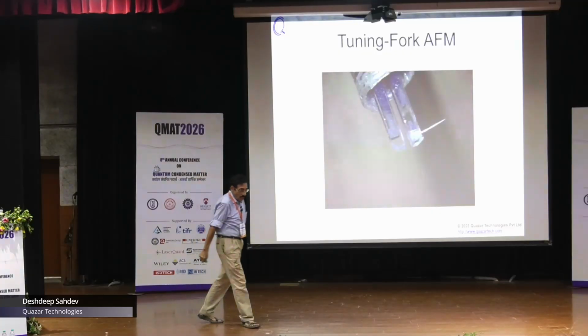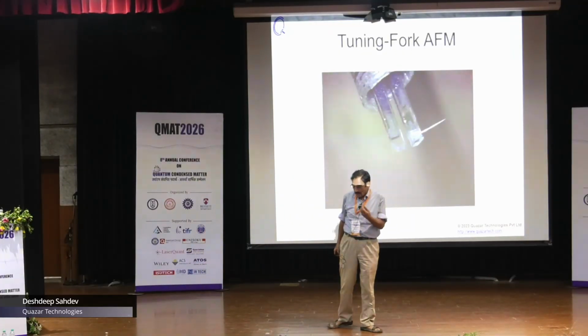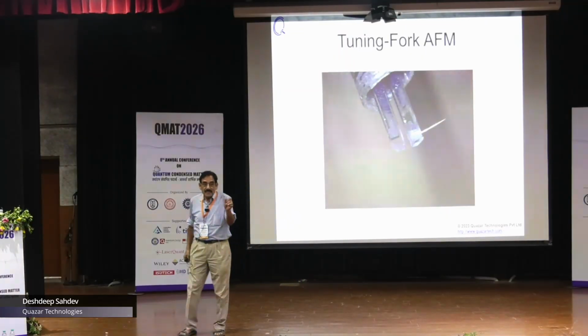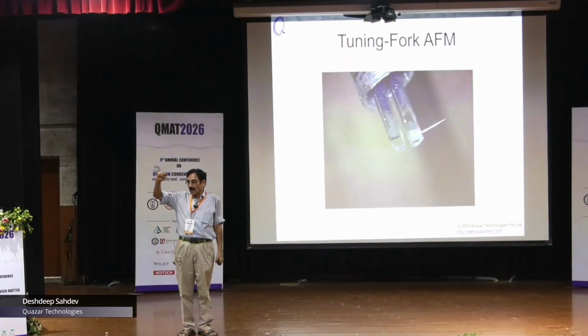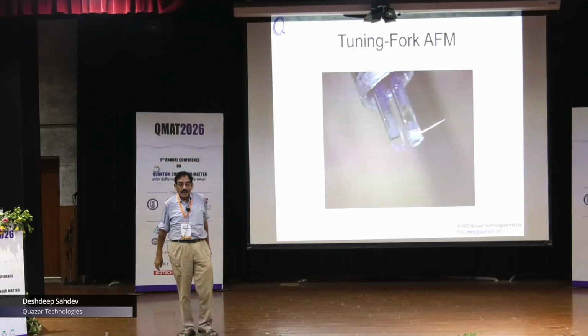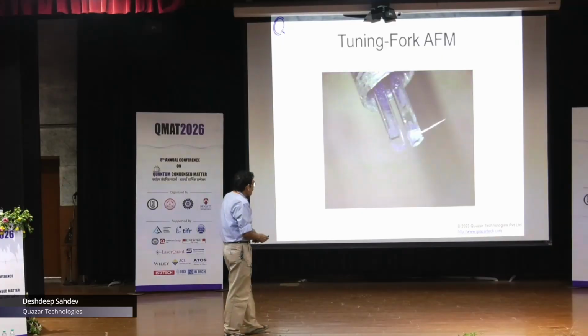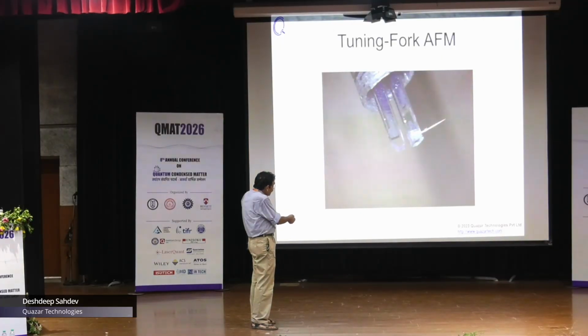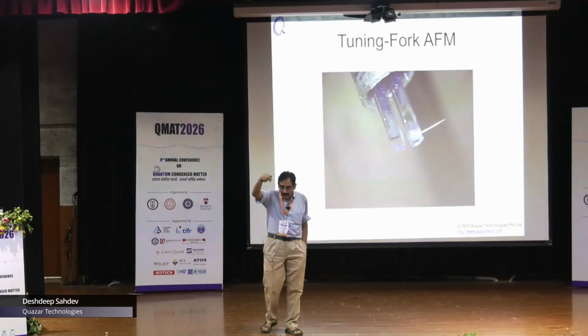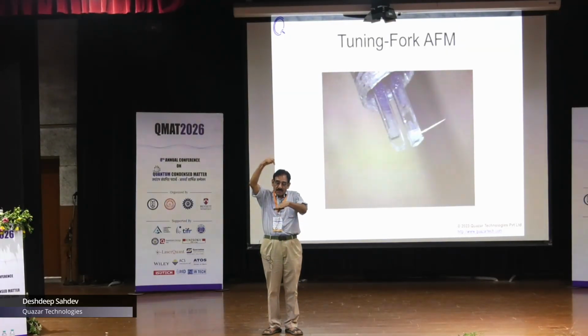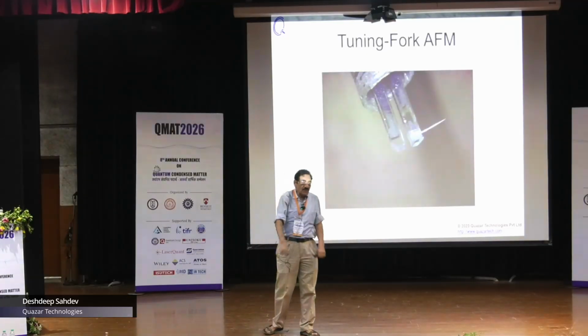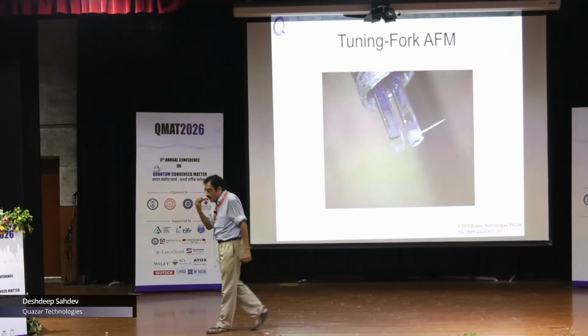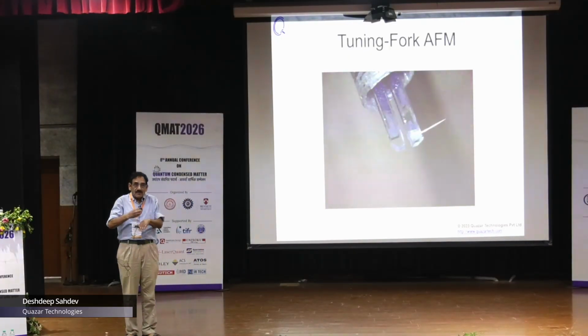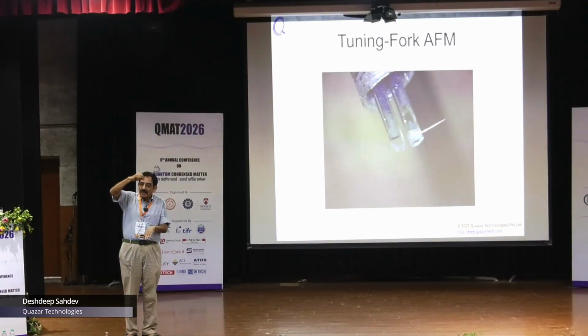This is fascinating because you can take one of these tuning forks that you get routinely as a part of electronics, open it out; it'll oscillate in vacuum before you open it out. It oscillates 30,000 times a second. You have to make a jig, which we did, with which we can attach a tip here, and then we can etch it so we get a very fine tip. You get it vibrating, and you bring it very close to the surface. And when you bring it very close to the surface, the tip begins to feel the van der Waals forces. And those are attractive, so it tends to stick there. And just that hesitation, because it hangs around there for just a little longer, increases the time period.